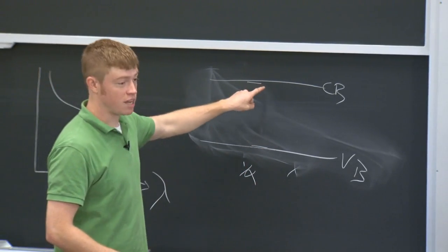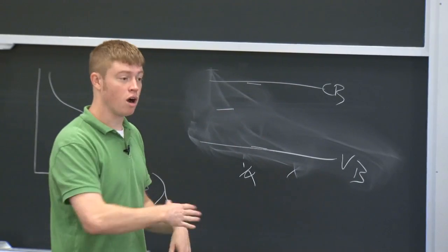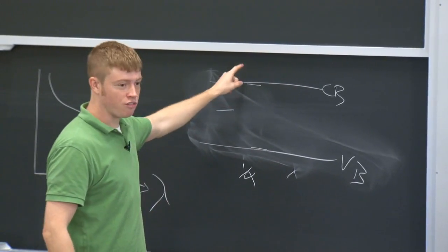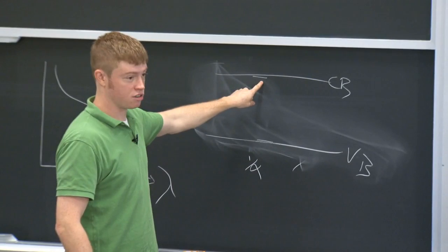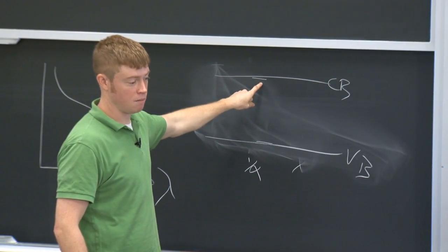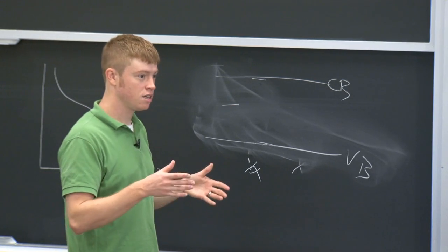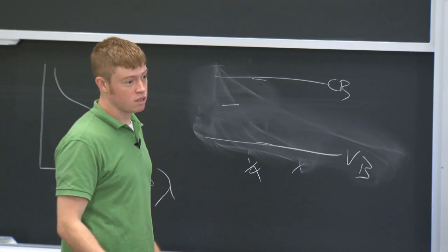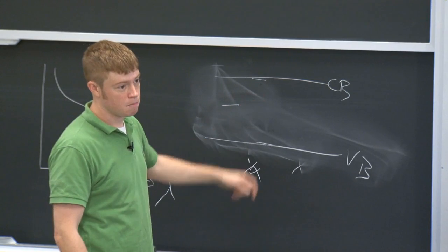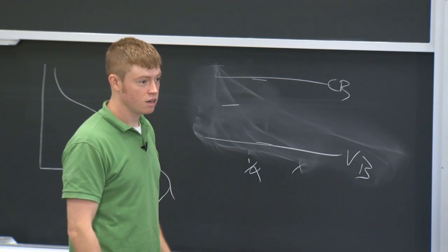If you go to low enough temperature, so let's say below 100 Kelvin, you can actually freeze out those donor electrons onto the phosphorus atoms. And below certain concentrations of phosphorus atoms, for example, below like 10 to the 18, at 0 Kelvin, you cannot conduct electricity. It actually becomes a total insulator. This is an excellent question.